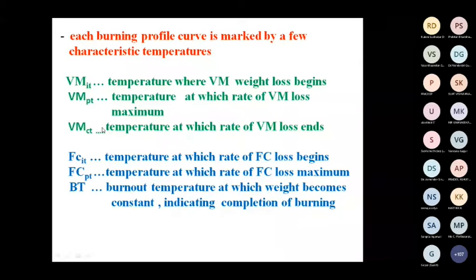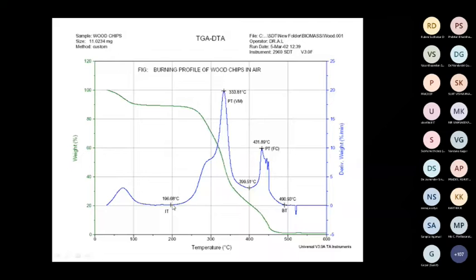VMCT. Then fixed carbon IT, FCIT, the temperature at which the rate of fixed carbon loss begins. Then the temperature at which the rate of fixed carbon loss is maximum, called FCPT. The last one is BT, burnout temperature, at which the weight loss becomes constant, indicating completion of burning. So VMIT is the start of volatile matter, VMPT the temperature at which volatile matter burning is maximum, then VM completion, then start of fixed carbon, the temperature of maximum fixed carbon burning rate, then BT, the final temperature, the completion of burning.